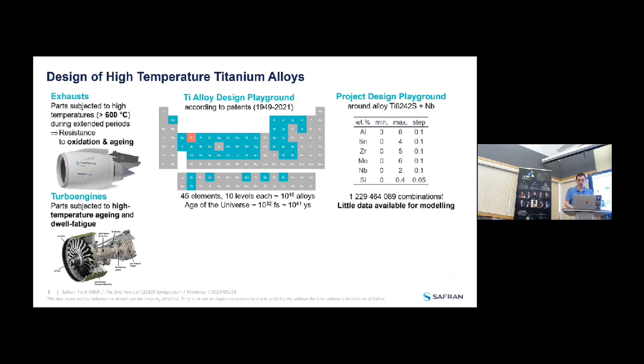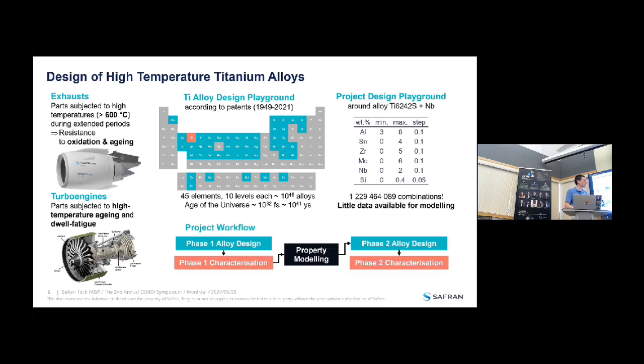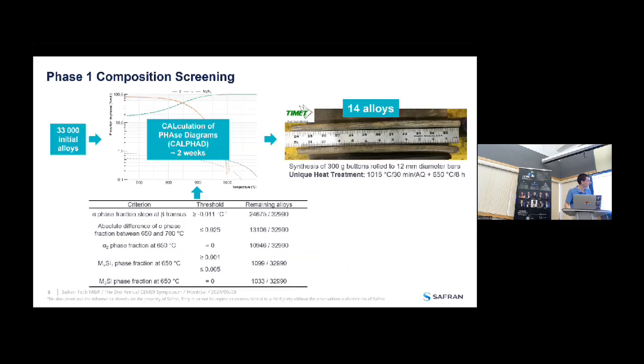So the actual playground was revolving around, let's say, the outskirts of a commercial alloy, which is called TI6242S, to which we added niobium, and the idea was to minimize the number of combinations that we had to consider. But the problem is that we didn't have any data to start with. So we had a two-phase project, where in the first phase we did some naive alloy design to generate data for the model and then used this model to optimize the composition of phase two alloys.